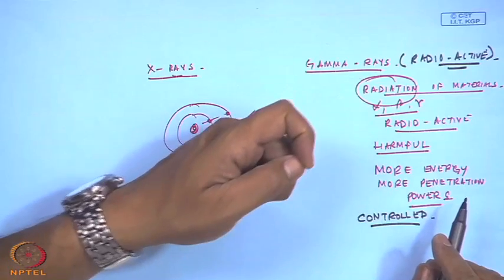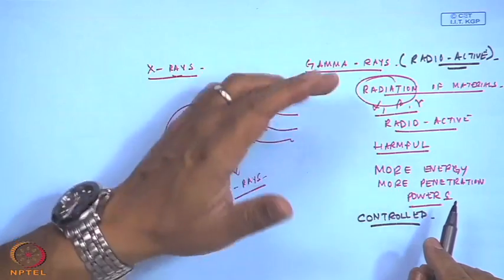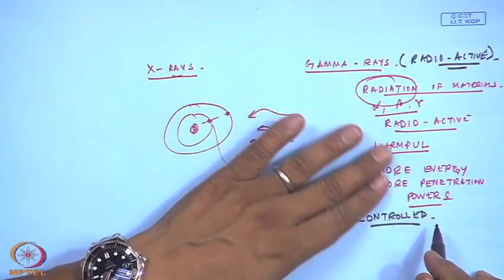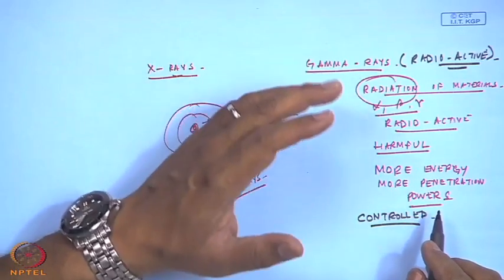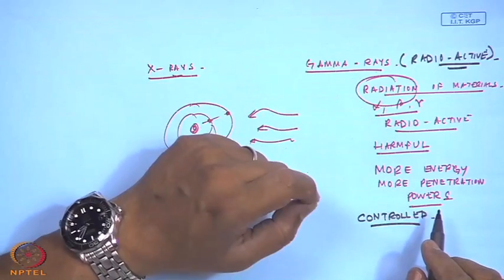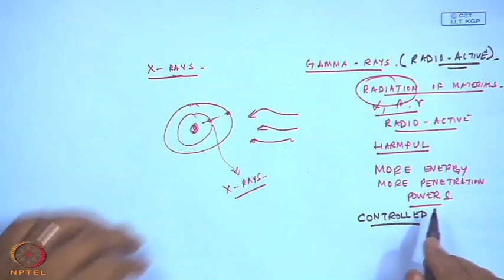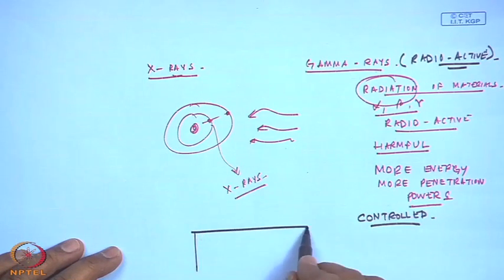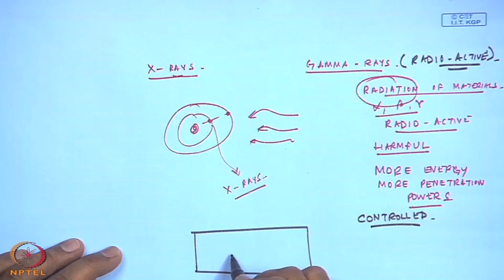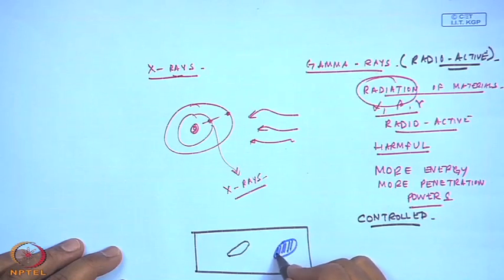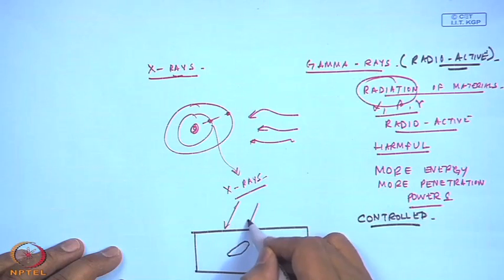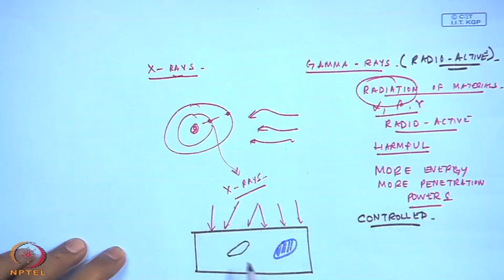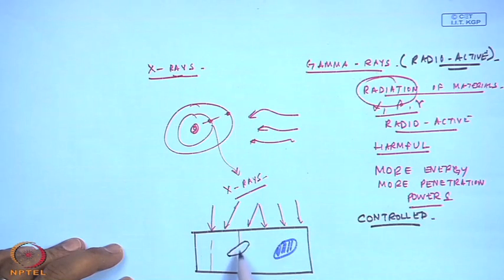People use gamma rays because a small amount of nuclear material can generate them, and they can be controlled and used for NDT testing. The key — be it x-rays or gamma rays — is that we use the energy of these waves to penetrate a material. Like in ultrasonics, if we have a material where there is a void or a foreign particle of a different density, and x-rays are incident on this material, they will penetrate and because of the density difference, the intensity of the x-rays at that location will be different.